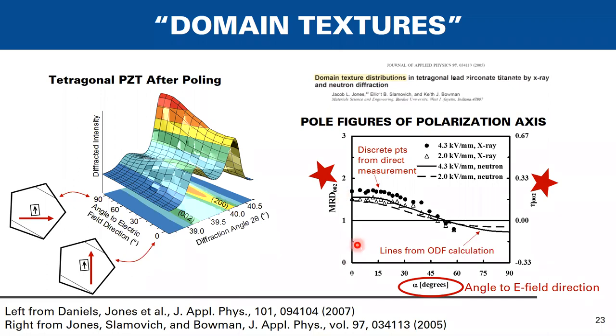Now, there's a couple different techniques we used to create this pole figure. We did a couple neutron scattering experiments and calculated the full ODF. Those are represented as lines. And then we did some X-ray experiments in reflection. So we used a low energy X-ray source, and so we could only get over to a certain amount, but you can see that both measurements are fairly comparable.